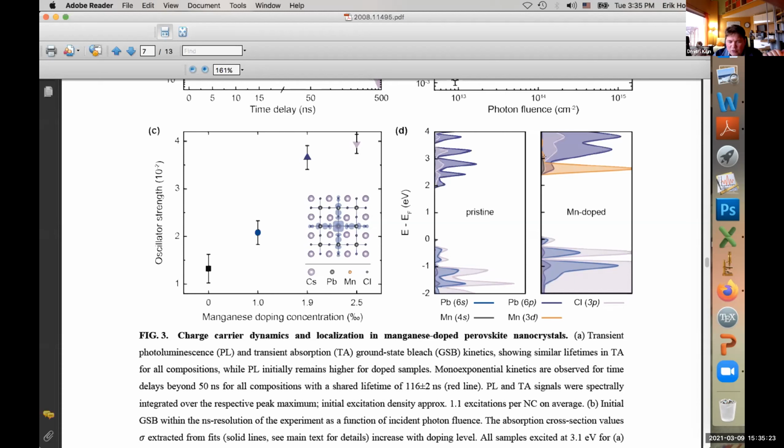Okay. So the only thing we can do today is to manipulate the concentrations. If we go to a limit of very small clusters, confinement shifts HOMOs and LUMOs to higher energy on one hand, and with very high concentration of manganese and also specific functionals, then we can get correct alignment of levels. But it will be hard to defend because the atomistic model is a little bit different from what is in the experiment. So I see the challenge. Yeah.